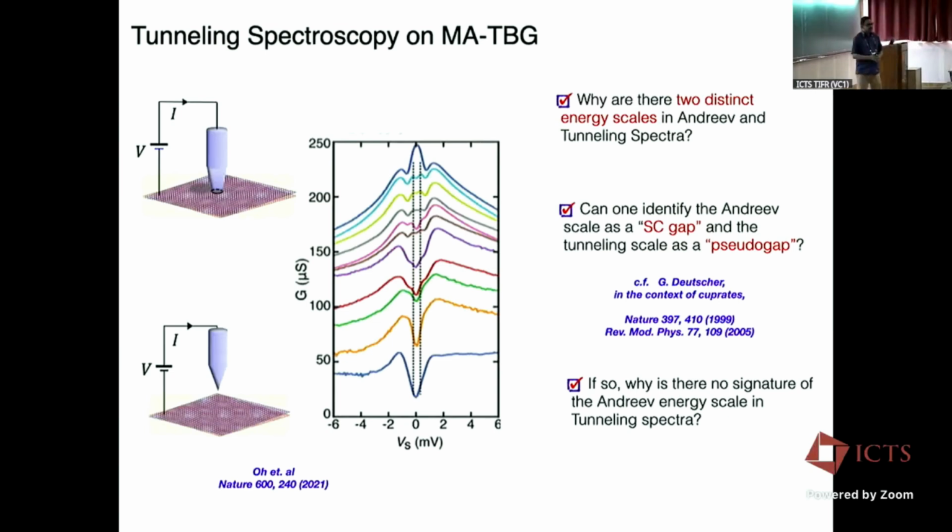Maybe the answer is that your superconductor is very strongly interacting, it shows pseudogap physics, there are two different scales, one for forming the superconducting coherence, one for some, this is without telling where the pseudogap comes from. There's another scale, maybe formation of Cooper pairs, maybe something else. And what you are doing in these two experiments is probably you are looking at the two different scales. That's one possible answer to the question.